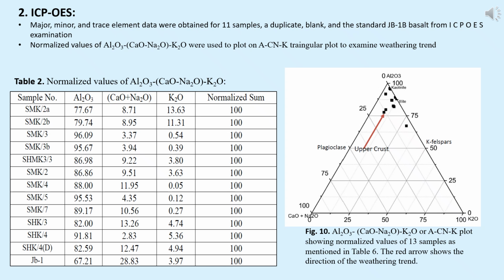It can be suggested that the large amount of kaolinite and illite is a chemical weathering product of plagioclase present in basalts of the Deccan Trap. Also, values plot more on the aluminum oxide side, which is an important oxide component in kaolinite and illite. This confirms our findings from previous tests of XRD and ICP-OES.